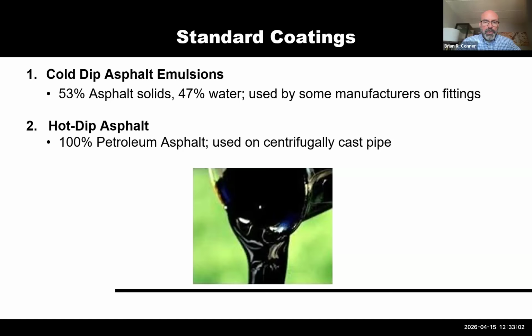So, for most manufacturers in North America, they use varying degrees of coatings, two separate ones really for both the pipe and the fittings. So most fittings in North America come with an asphalt emulsion cold dip, which is 53% asphalt solids and then water. Most of the manufacturers in North America use this on their fittings. At Charlotte Pipe, we do not.